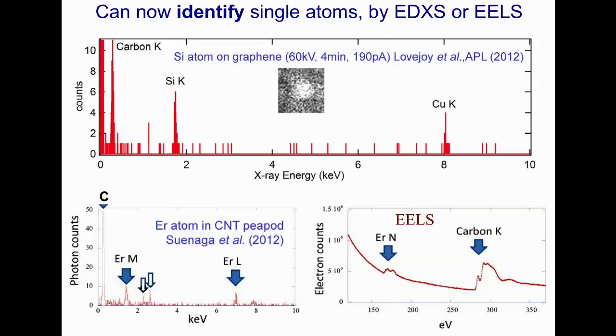In the X-ray spectrum on the left, the large blue arrows identify M and L line peaks that are characteristic of erbium. The smaller arrows point to molybdenum or sulfur and chlorine peaks arising from stray electrons hitting the molybdenum support grid and from traces of the solvents used in the specimen preparation. In the energy loss spectrum on the right, an erbium atom is identified from its N-shell ionization edge, and of course there is a large carbon K edge arising from the fullerene and nanotube components of the specimen.